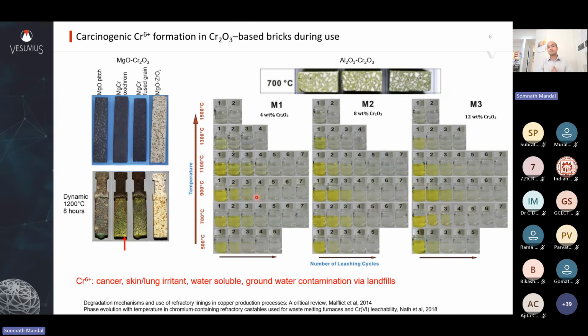And because of this problem, a lot of the countries are very strict. They restrict the hexavalent chrome content in the used refractories to less than 5 ppm, sometimes even less than 2 ppm. And this has caused mag-chrome to be banned from several countries and several places, and that's where a lot of the impetus has come to develop chrome-free refractories.